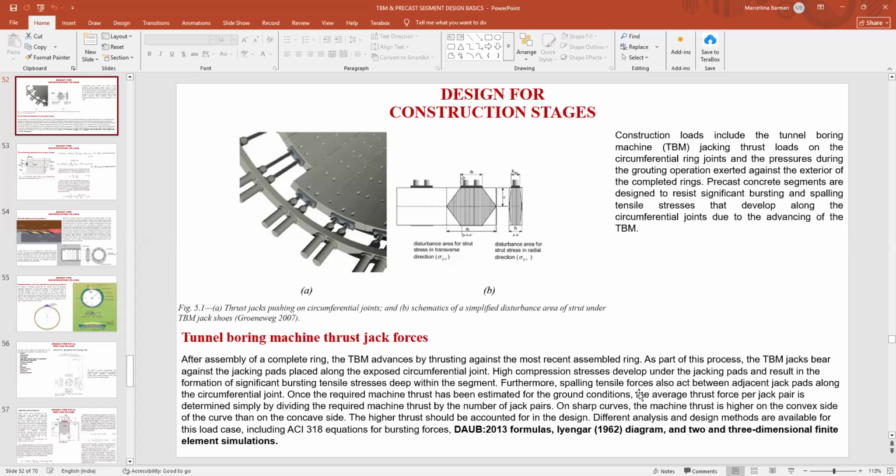In our Ahmedabad Metro project, as per the AFCONS standard mix design and the chemical and groundwater results we got from the GIR, when we compared these results and defined the exposure class, we got a design life of around 250 or 300 years. I cannot remember exactly, but it was more than 100 years. After that the GC approved the design, because until the 100-year design life is verified, your design is not complete or cannot be validated.